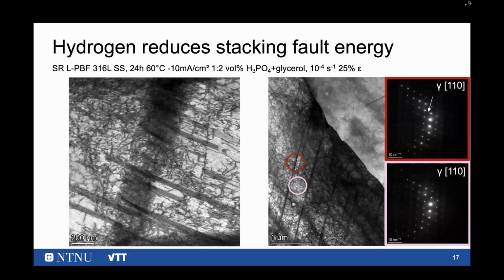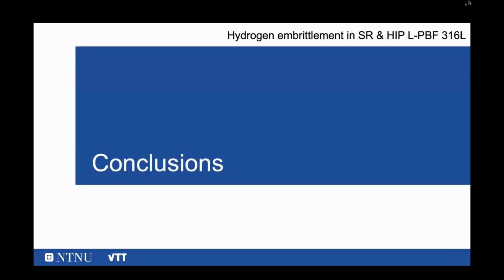There is a difference between, for example, this line and without this line. In this line, maybe it's not very well visible, but there is a line in between which indicates that there are more stacking faults, probably introduced by hydrogen. But this stress relief structure still has a good resistance against these hydrogen effects.